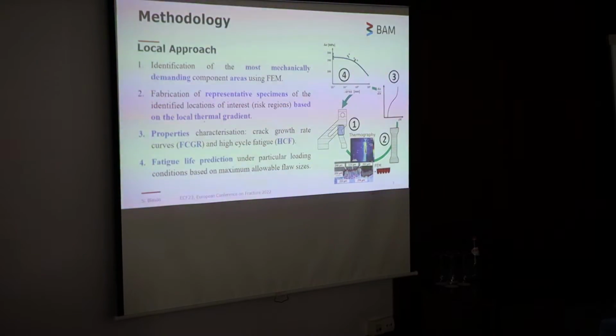So this is the main idea of the methodology that we are proposing. First of all, we want to identify, using simulations, the most risky area in the component. And from that point, we are going to identify the evolution of the temperature along the manufacturing process. From that point, we want to check the performance of the material by doing, in this case, crack propagation tests and also high cycle fatigue tests. So basically, we are interested in fatigue properties. And from that point, we want to reproduce representative specimens, which means that we want to reproduce the same behavior of the original component, but not using specimens extracted directly from the component, but specimens produced ad hoc. And from that point, we want to check the fatigue performance of the material.